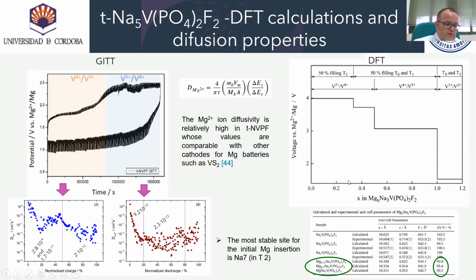On the right, it is shown the calculated voltage as a function of magnesium content in the composition of the t-NVPF. According to calculation, the most stable site for the initial magnesium insertion is the sodium 7 in tunnel T2 at 4 volts. After this first step, the calculated voltage for the insertion in tunnels T0 and T1 is very similar. The calculated volume variation during the insertion of one magnesium per formula unit to give this composition is less than 1%, making this material an interesting candidate for magnesium insertion.